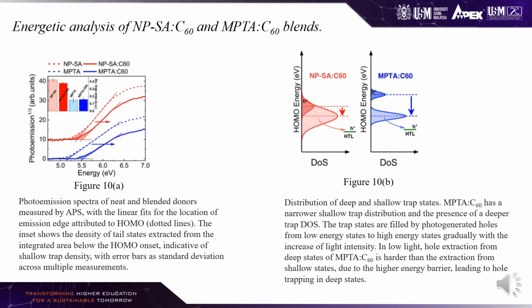This slide shows the energetic analysis of NPSA carbon-60 and MPTA carbon-60 blends. Figure 10a shows the photoemission spectra of neat and blended donors measured by APS, with the linear fit for the location of emission edge attributed to the highest occupied molecular orbital. The inset shows the density of tail states extracted from the integrated area below the highest occupied molecular orbital onset, indicative of shallow trap density, with error bars as standard deviation across multiple measurements.